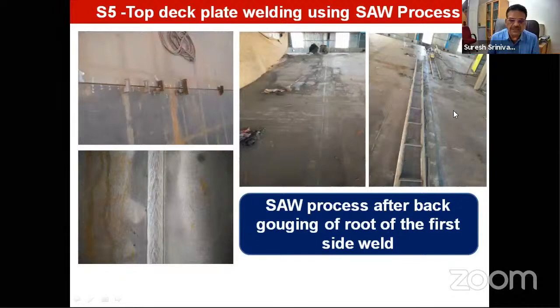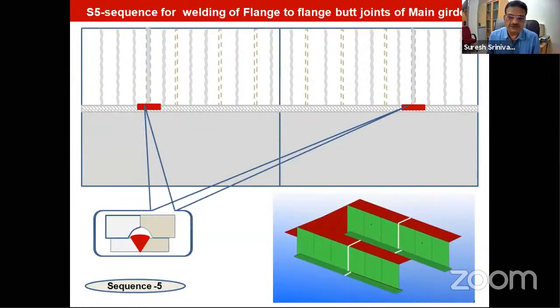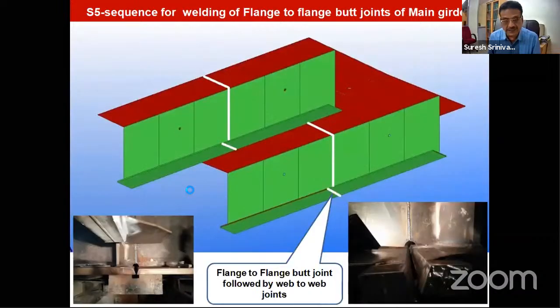So after completion of welding, we come to the top where we do the SAW welding after back gouging of the root and the first side weld. We do the final welding with the semi-automatic welding and test it by mechanized phased array UT, where the data was completely logged in the computer and it was evaluated by various inspection people as well as UT experts to clear this weld. So this is the challenging job here.